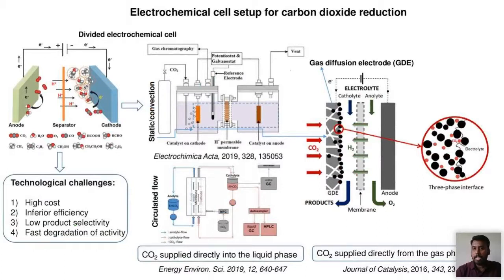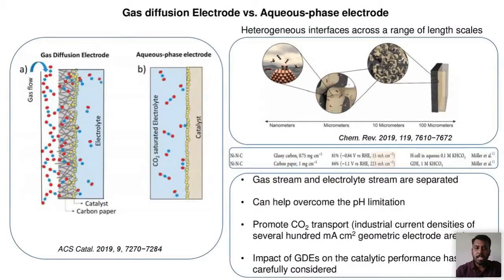And the electrochemical cell setup is very important for all these reactions, whether it is a half cell or a full cell. You should separate your electrodes, and also you should have a static flow or a circulated flow to improve the mass transport. Gas diffusion electrodes, where the gas can be directly fed to the catalyst surface, can minimize the mass transport limitations. So gas diffusion electrodes always have a much higher advantage than aqueous phase electrodes, because the gas molecules are directly fed to the catalyst surface without the need to diffuse through the electrolyte. The gas stream and electrolyte stream should be separated, and it can help overcome the pH limitation, and it can help with the CO2 transport.